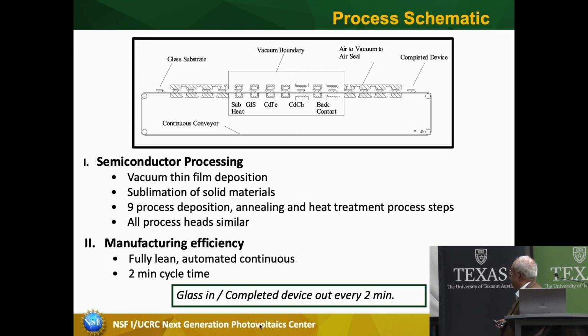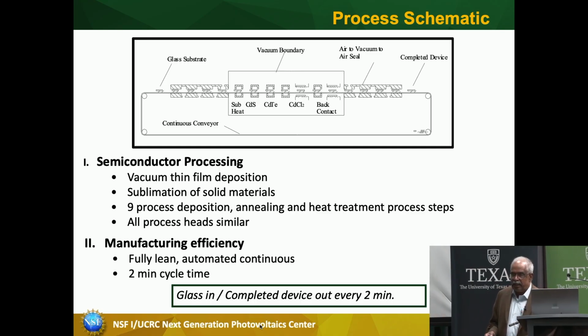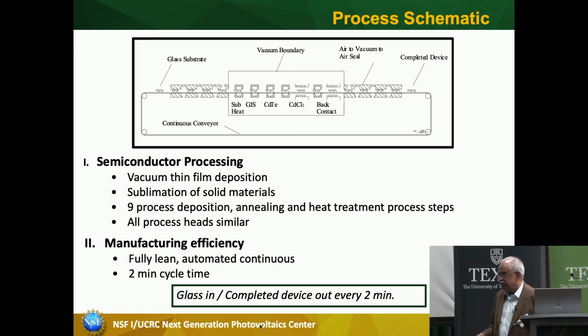We did do quite a bit of work on the back contact. When we started in 1991, the consideration was cadmium telluride cannot be made to work because back contacting is hard. You need copper for back contacting, and copper is unstable because it moves in. It's still a prevalent theory, by the way, but the point we brought out, and this is our key contribution to the cadmium telluride technology itself, is that small amounts of copper, well controlled, well done, you can have acceptable stability.